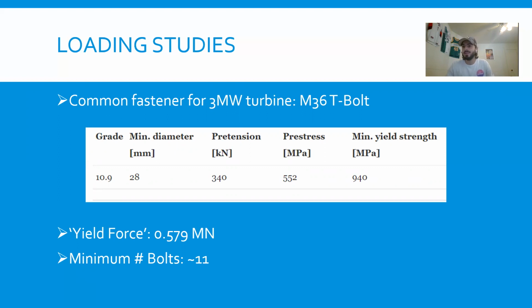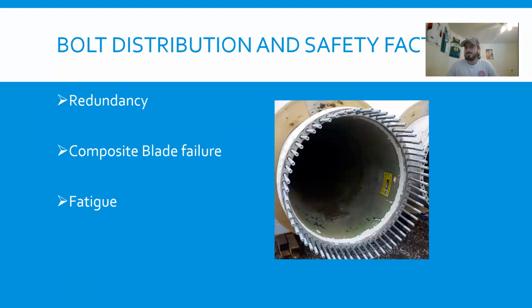So let's talk about why we might want more than 11 bolts, even though technically we could handle it. Of course, you guys are familiar with safety factor, but just to really hit it home, redundancy is very important. We don't want to have it that if one bolt fails, the entire thing falls apart, which is why we have plenty of bolts. One, it keeps the loads lower per bolt, but also it just helps in case one bolt does fail, there's others to pick up the slack. Additionally, as I mentioned before, the material difference between steel hub and composite blade makes loading kind of difficult, right? Although these 11 bolts could handle all of the load, it would create stress concentrations in the blade itself, in the composite blade, and likely would just rip right through the blade, still leading to ultimate failure or catastrophic failure of a blade throw. So we need to keep the bolt loads low enough that we don't create stress concentrations in the blade itself and rip through it.